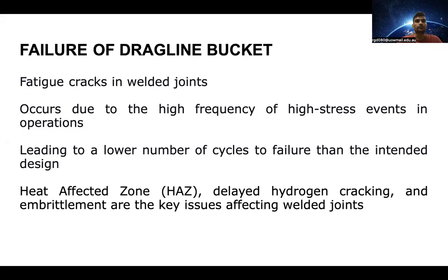Now let's look into some of the key reasons for the failures in dragline buckets. Based on all the research studies and literature review that has been done, the main failure of dragline buckets is due to fatigue cracks in the welded joints. Now we need to understand why these fatigue cracks occur in the first place. They occur because of the high frequency of stress events during operations. This leads to a lower number of cycles to failure than intended.